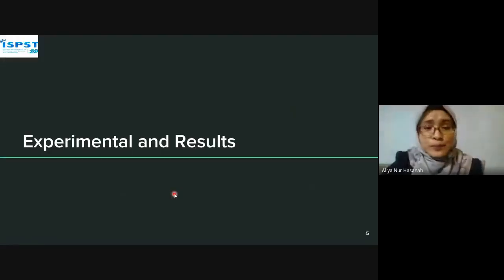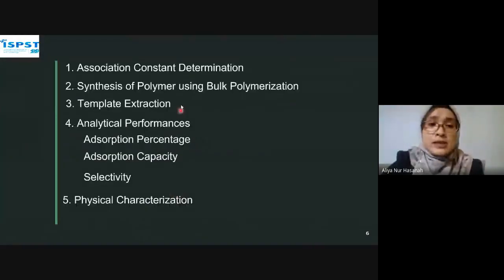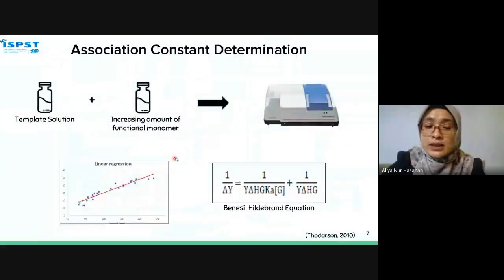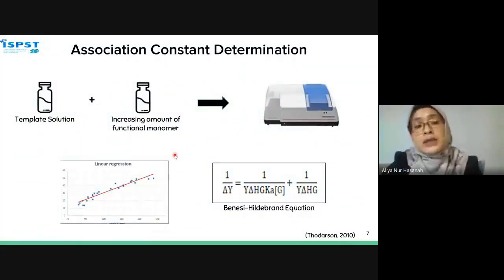We continue with the experimental and result. This will consist of association constant determination, and we will end with physical characterization. For association constant determination, to find out the association constant between the functional monomer and the template, we measure the absorbance of the template solution, and then we increase the amount of functional monomer used, and we measure again using a UV spectrophotometer. The result of the measurement is plotted into a linear regression, and we calculate the Ka value using the Benesi-Hildebrand equation.